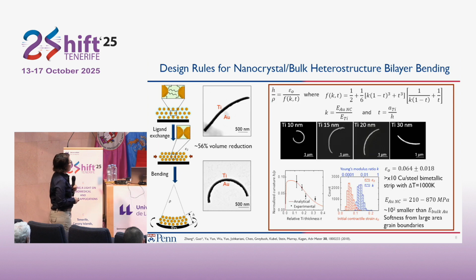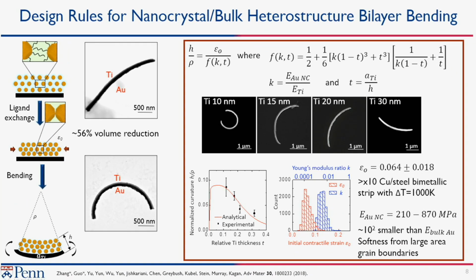And so what we did is we made many structures where we controlled, for example, the thickness of the titanium layer. And as you can see here, as you make the titanium layer thinner and thinner, you can see that these structures curve more and more.